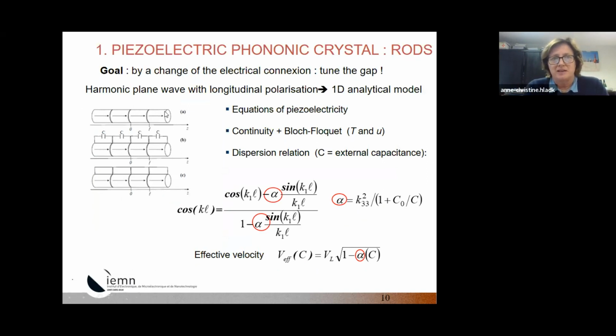Here you see a stack of piezoelectric rods. They are all poled along their thickness, and between all the rods you have some electrodes. And you will change the connection on the electrodes of the rods. So we imagine that a harmonic plane wave is propagating with longitudinal polarization, and we have developed a one-dimensional analytical model. First we have written the equations of piezoelectricity, and we have written the continuity and the Bloch-Floquet equations for the stress and for the displacement. And then we have solved the equations, and we have got the dispersion relation that is here.